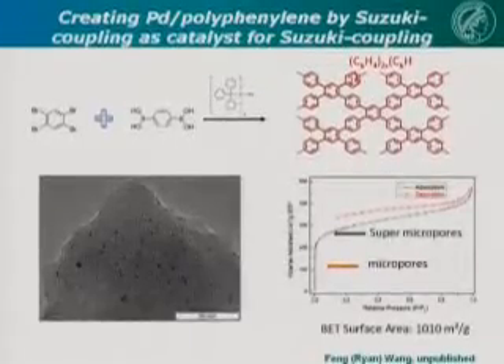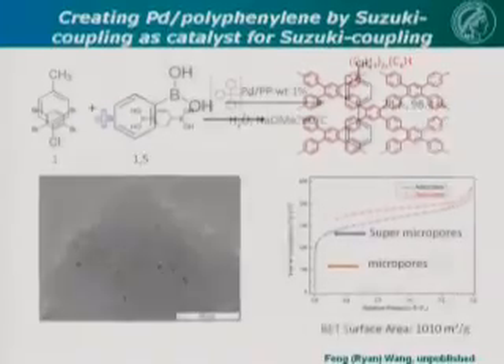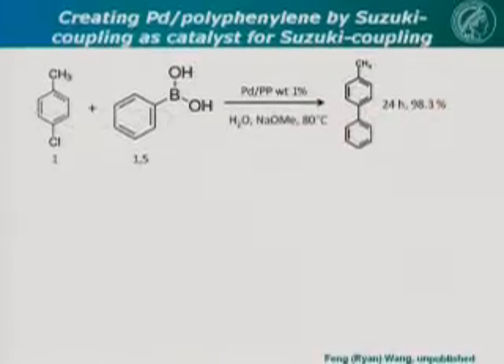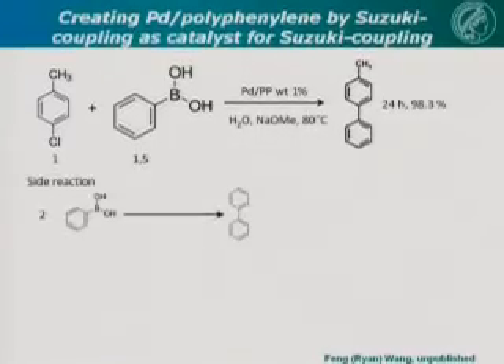Well, it's a microporous material, so BET surface area has to be interpreted with care, but it's a very porous material, roughly 300 cubic centimeters per gram. Pore volume, if you calculate something like a BET surface area, it's about 1,000 square meters per gram, so it's a highly porous material. And if you use that for a standard Suzuki coupling, it's actually a pretty good catalyst. In 24 hours, almost 100% yield.